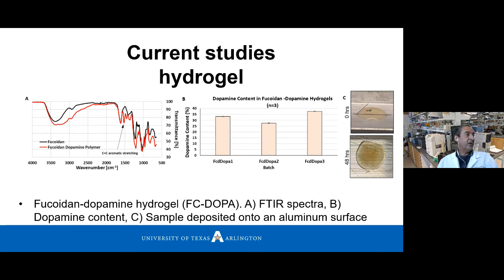We confirmed the conjugation, as you can see in the image under the letter A. And we have been preparing these materials with concentrations of about 35% of dopamine. And in the pictures on C, we deposited a droplet, a sample of the material, onto an aluminum surface to observe the way it adheres. And we first observe a very low contact angle, which is evidence that the material is spreadable and can easily get in contact with the surface.